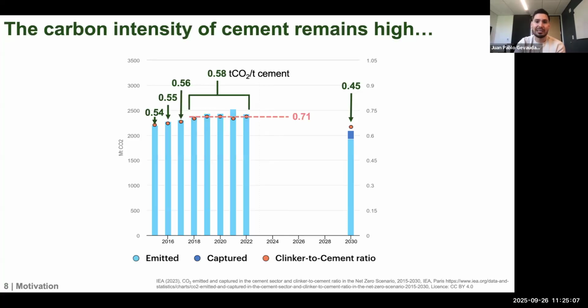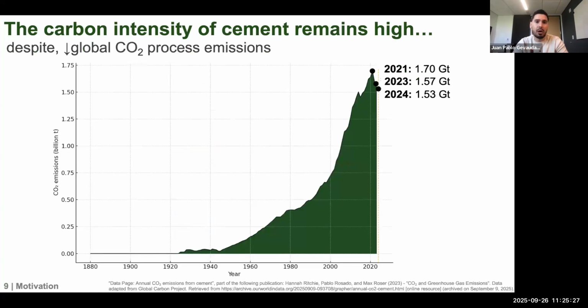So all that is to say, the carbon intensity of cement remains quite high still. But what has happened over the last few years? I couldn't find any data on that, so if anybody has data over the past few years, I would love to see it. But what I did find is the CO2 emissions for the process emissions from cement manufacturing globally. And what we see is that since 2021, we actually have been decreasing the amount of CO2 emissions from cement manufacturing, which a lot of you may think, wow, this is really great news in terms of the total volume of CO2 emissions due to cement.